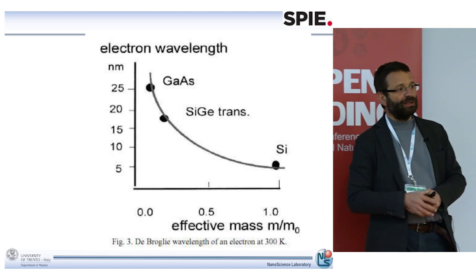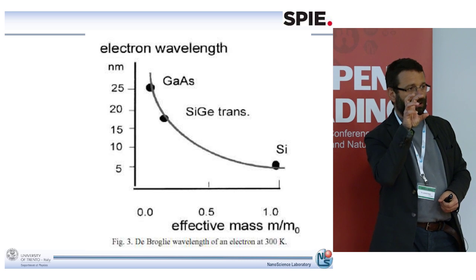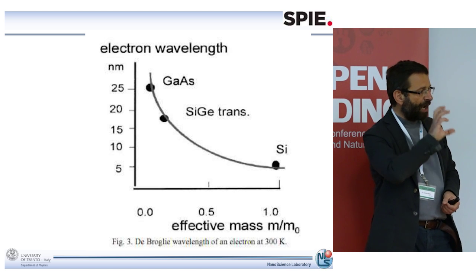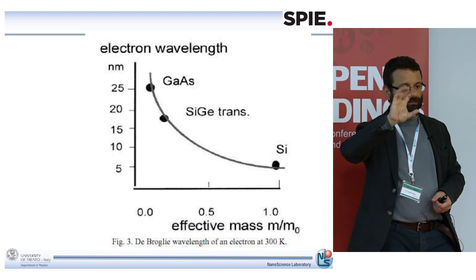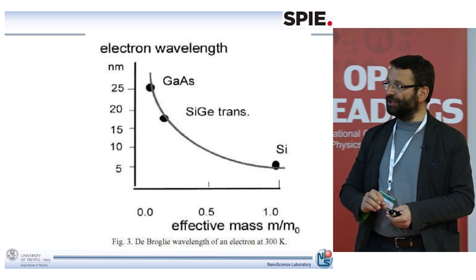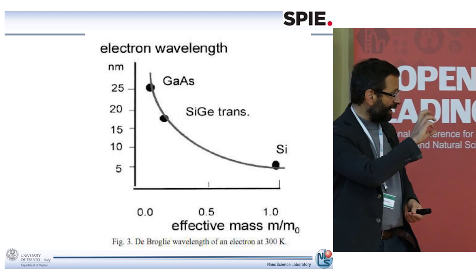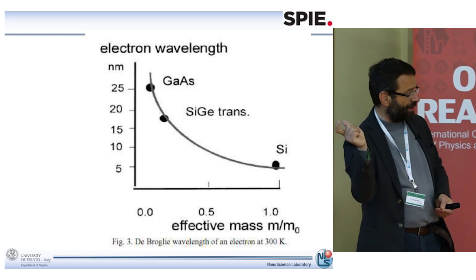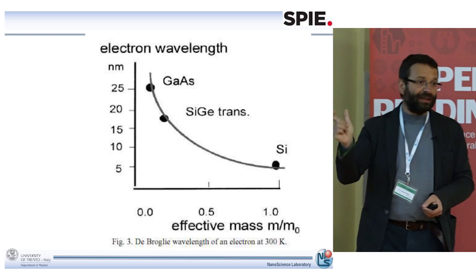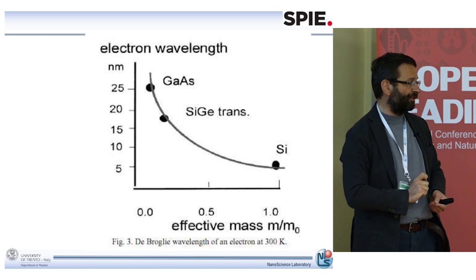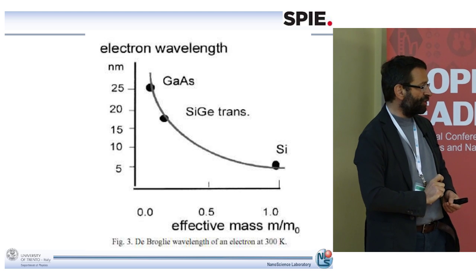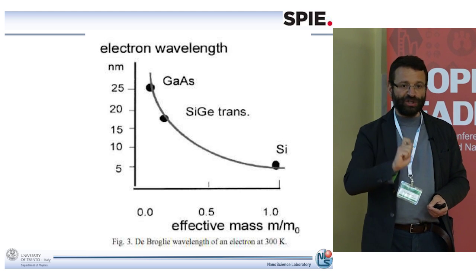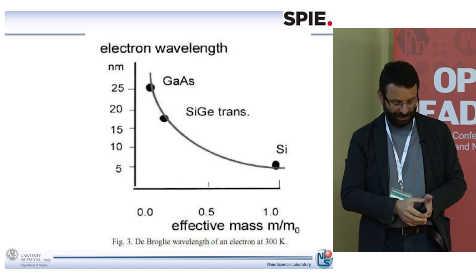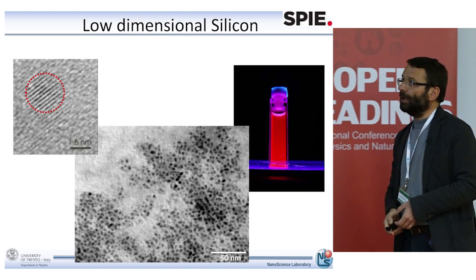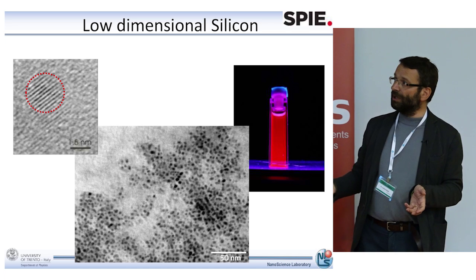So that means that if we want really to beat the indirect band gap of silicon, and enter the quantum confinement regime, we need to make this silicon so small that the electron de Broglie wavelength is similar to the dimension of the silicon nanocrystal. So we have to reduce the dimension of the crystal to a few nanometers. And this is what actually we are able to do.